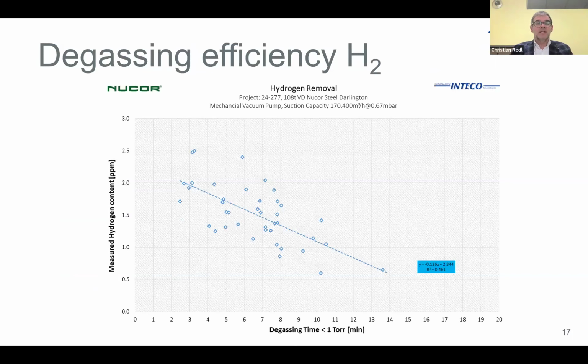To give an example of the degassing efficiency, this is taken from Nucor Steel in Darlington, which I showed you before. So here you see the clear trend. The longer you have the degassing time below 1 torr, the lower the hydrogen content will be. So here we see with a degassing time of 8 minutes, we are in a range of 1.5 ppm hydrogen content.